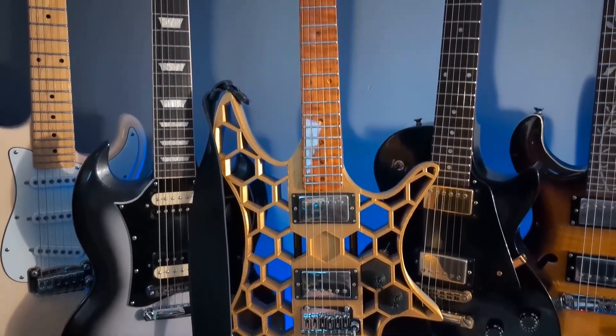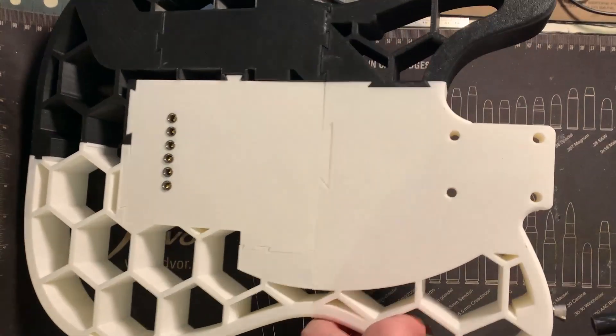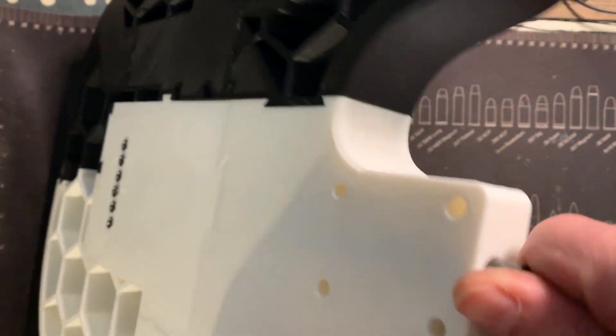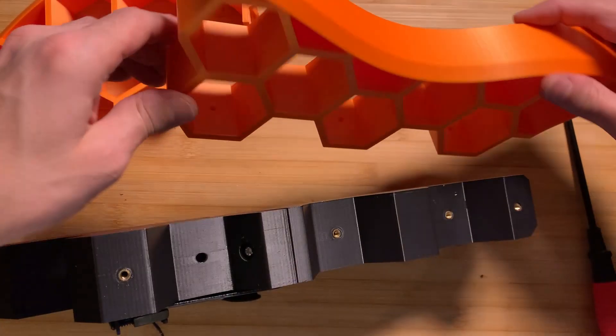I have two other 3D printed guitars. The other two, because the bodies aren't reinforced — one of them has a single carbon fiber rod, and if I leave it under string tension for a few days, the body and neck kind of start to bow in a little, not that much, but enough that it affects tuning. The other one has no reinforcement. The other two were printed in pieces and then put together. I used CA glue — like a super glue, a cyanoacrylate. I think I should have used a different type that vulcanizes and melts it together instead of CA glue.